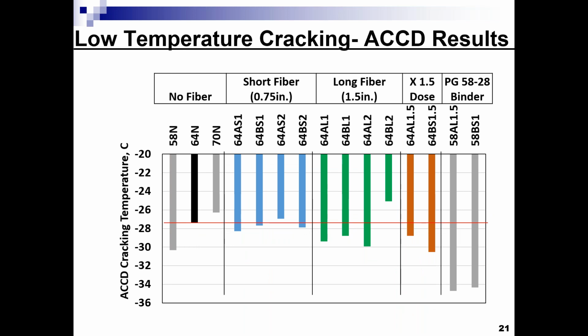If we go to the low temperature cracking, what we have seen in general is that the fiber mixes did not really improve the cracking. There is some improvement or some changes, but those changes are not significant enough to say that there is an effect of the fibers on the low temperature cracking.